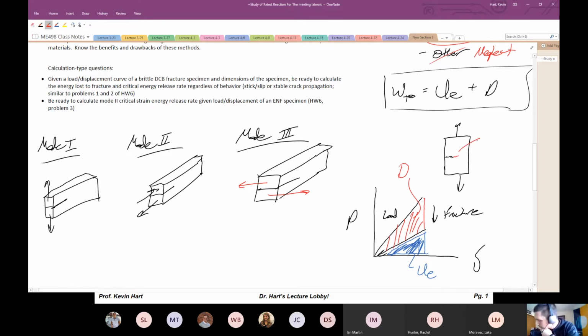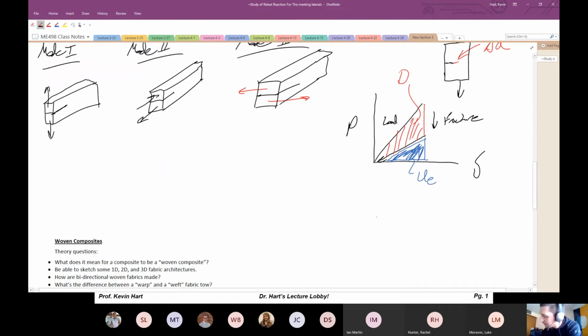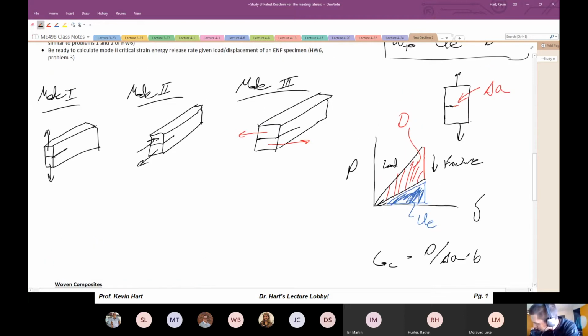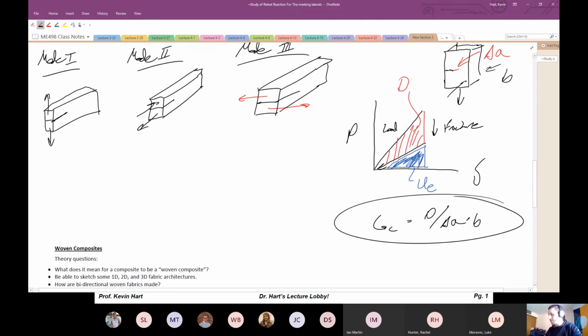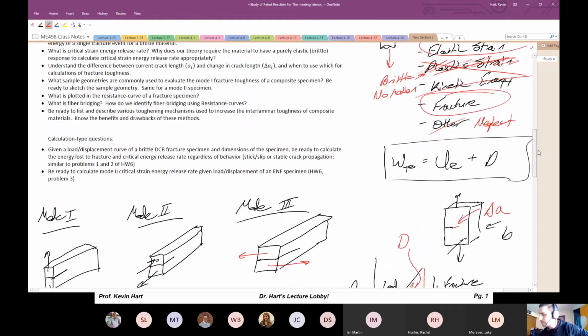So if the crack advance, this delta A, has the energy associated with it, which is this capital D, then we say that the critical strain energy release rate, which is GC, is just equal to fracture energy D divided by the crack advance length delta A times the width of the piece into the page, little b. We assume that this has some width to it. So this is your critical strain energy release rate. It's in units of something like joules per meter squared. Energy required to open the crack a certain area. Energy per crack opening area, joules per meter squared. And that's your fracture of a brittle material.